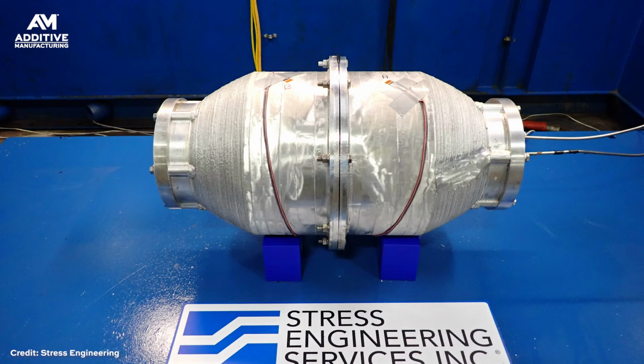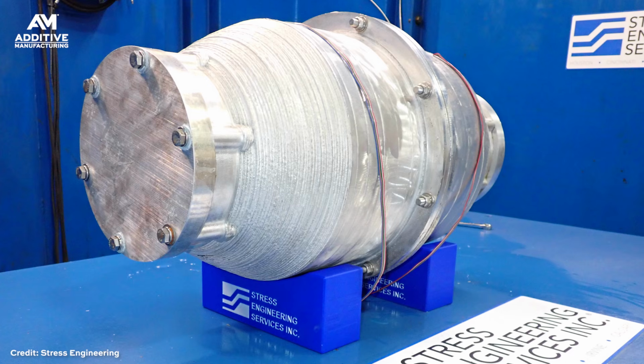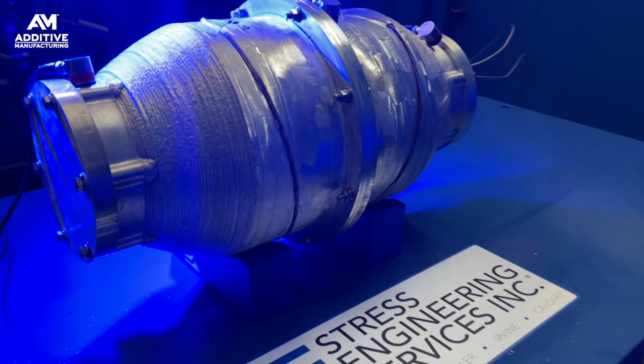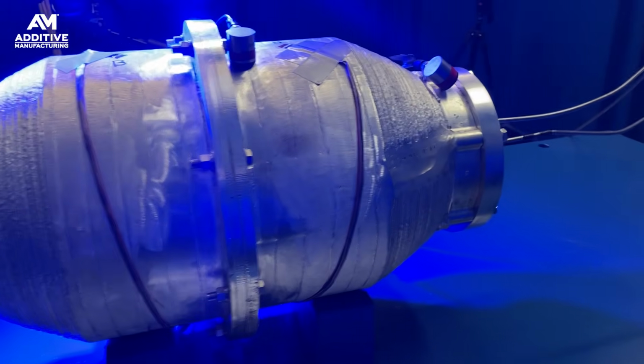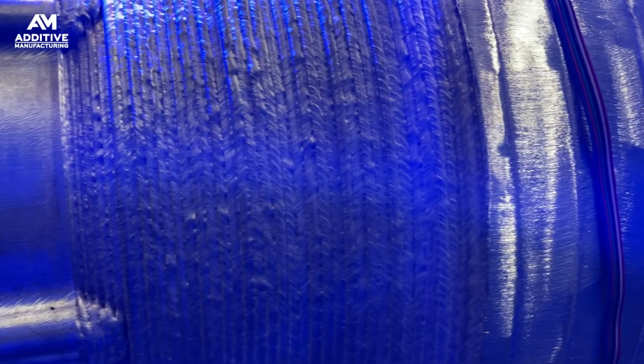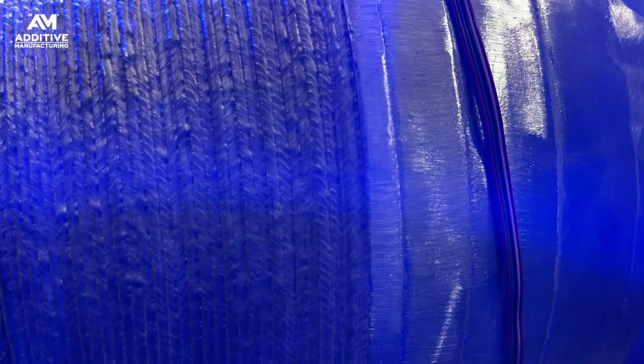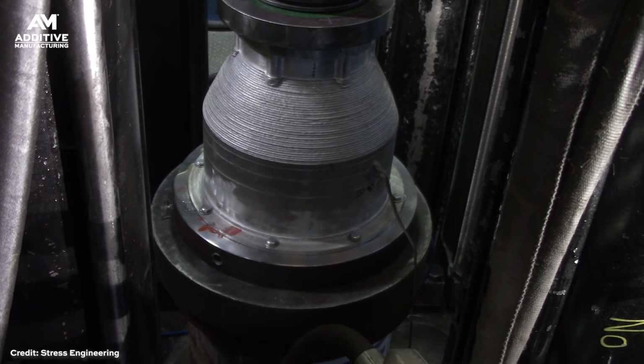Taking it all in context, what does this set of tests show us about 3D printed pressure vessels and about wire DED in general? I asked Matt and Slade for their takeaways. So the conclusions we can draw from all this testing is that the additive material really performed well. In fact, it outperformed a lot of the non-additive parts that were incorporated into it. And the design features from additive that allowed for very complex geometries, even under fatigue and other loading conditions that it's not really designed to see, the additive material performed very well.